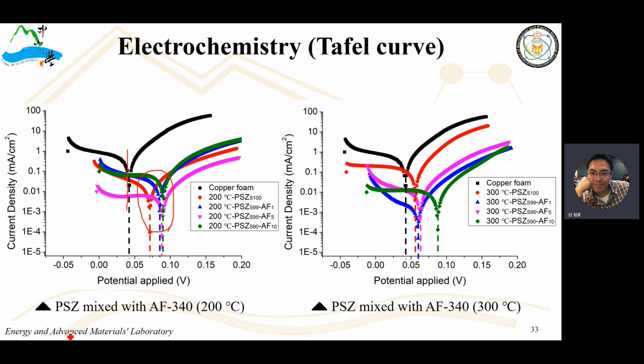Do you still remember we need a higher corrosion potential, right? We need higher corrosion potential and what? And the lower corrosion current. Okay, so do we have it? Of course, right? So from here, this is the corrosion potential enhanced, and the corrosion current is reduced a lot. Then you can see that after the pre-ceramic precursor incorporates AF-340, its potential increase is higher than that of the pure precursor.